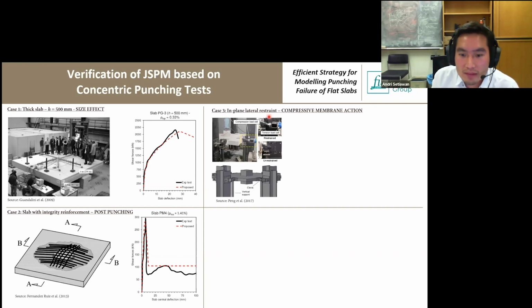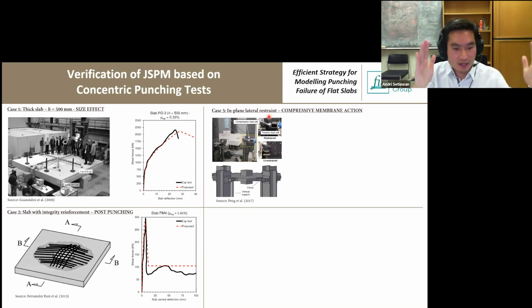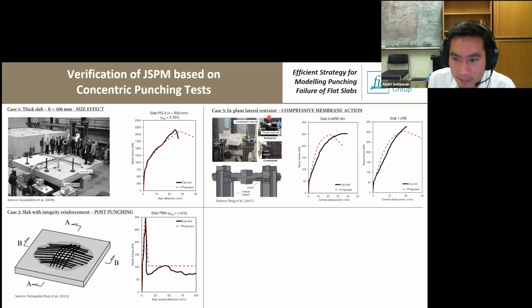This test was done by the University of Nevada, and they have a lateral restraining frame structure in order to prevent the slabs from expanding laterally when they crack. So we can have a lateral stiffening effect. We can see in here, for both slabs with a lateral restraining system, we are capable of capturing the load rotation and also the failure load quite accurately.